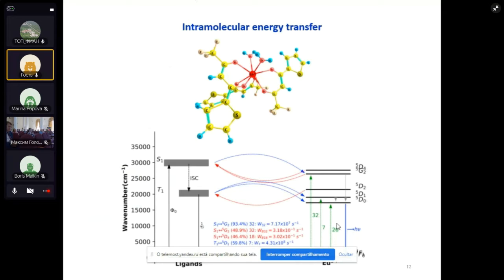And I will focus here on the case of europium complexes, just to illustrate, and intramolecular energy transfer in this case becomes very important, but we have to be very careful, because if the ligand levels, triplet and singlet excited states, are close to the plasmon band and also close to the excited states of, in this case, the europium ion, the excited states of the ligand would have to be included in the analysis. So it would be a good idea to choose ligands for this subject in which the excited levels of the ligands are above the plasmon band.